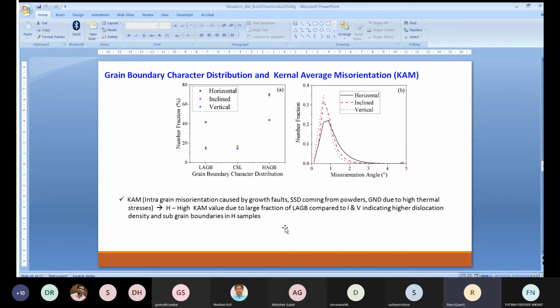If you look at the misorientation angle KAM value, the KAM value will give you an idea about the intra-grain orientation. I mean, you take a single grain, and inside it subgrains are there. How it is misoriented is easily understood through kernel average misorientation. Kernel average misorientation is caused by growth faults during solidification, statistically stored dislocations coming from the powders, and geometrically necessary dislocations coming from thermal stresses arising in the melt pool.